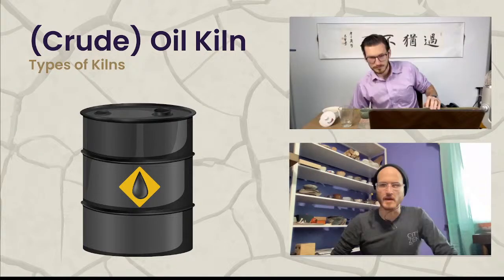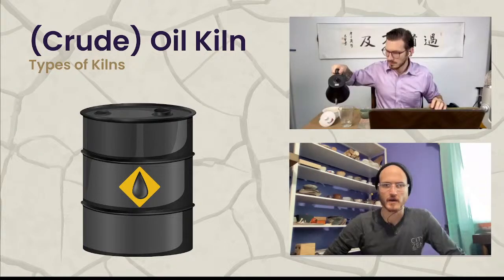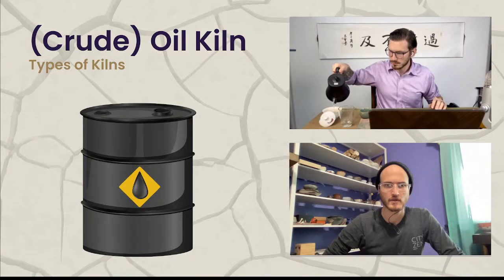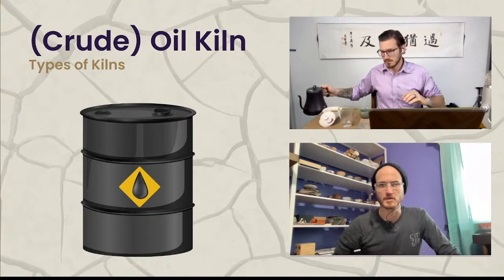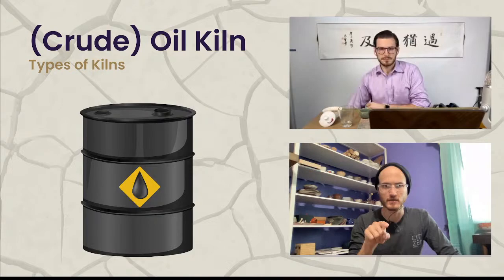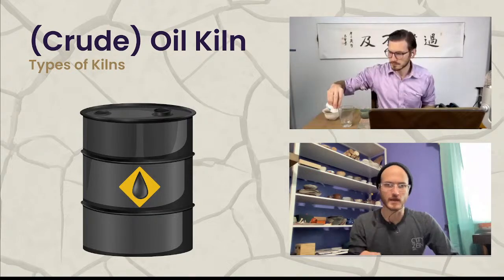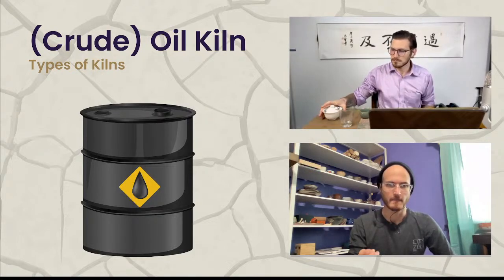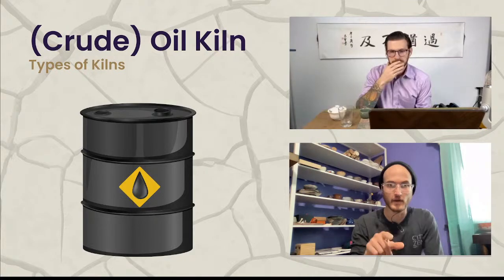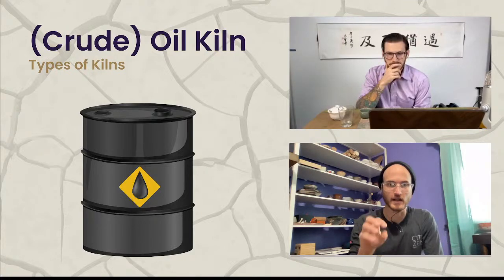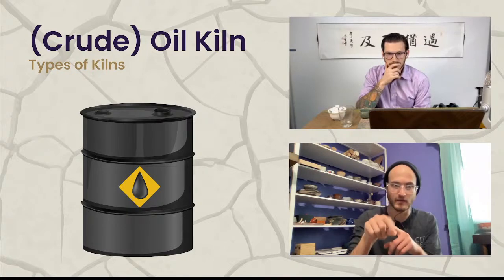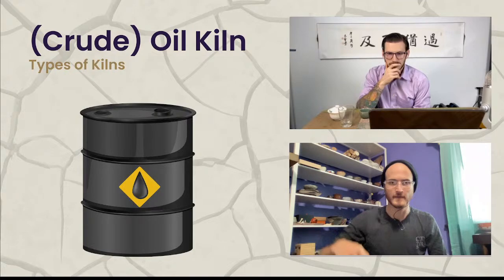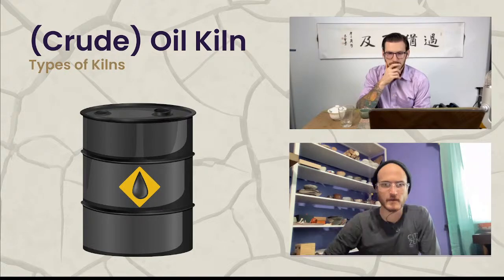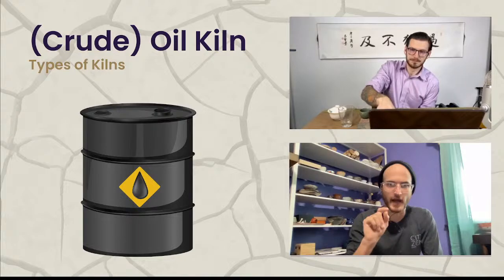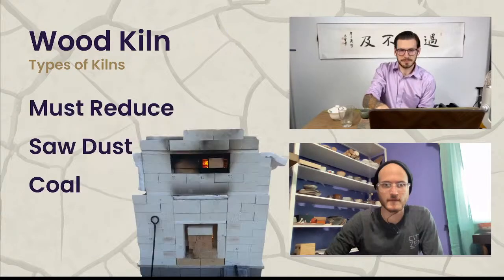What you might have been looking at might have been some sort of industrial drying kiln. For pottery kilns, usually it just looks like a spray nozzle. And so you would heat the kiln up first with like a small fire, and then you light the oil as it's being sprayed, sort of aerosolized into the kiln or dripped in, and then it burns in sort of a reservoir where it drips in. And that's usually how they work. Once it gets hot enough, though, it'll burn as it goes into the kiln, and it's more aerosolized.